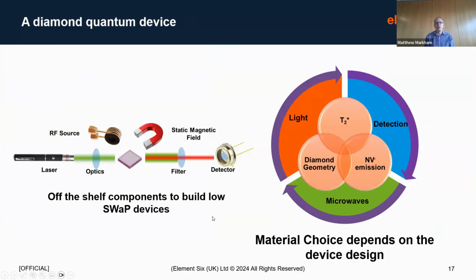So what does a diamond quantum device actually look like? I mentioned earlier, it's actually a relatively simple device, as we've shown here on the left. You just need a green light source. Here I've described it as a laser, but it can be an LED. It's not that fussy, to be honest, about the light source. That then shines onto the diamond containing these defects. You then apply an RF field at 2.8 gigahertz.